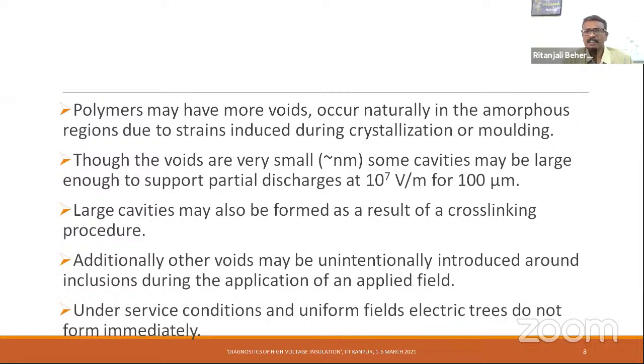Polymers have voids. They occur naturally in the amorphous regions due to strains induced during the crystallization process. In fact, there were reports that during manufacturing, it is the gaseous environment, and hence gas formation or voids forming inside is very much possible. Though the voids are very small, some cavities may be large enough to support partial discharges at a much higher field of about 10 power 7 volts per meter for 100 micron. Large cavities may also be formed as a result of a cross-linking procedure. So one of the issues with cross-linking is that void formation is very prone during this way of manufacturing. Additionally, other voids may be unintentionally introduced.